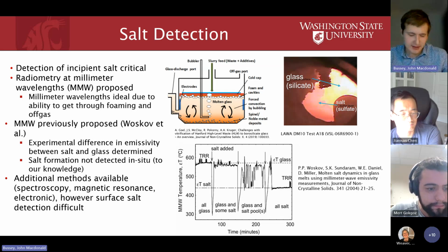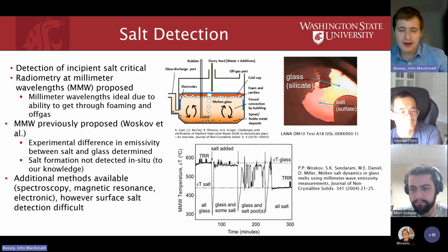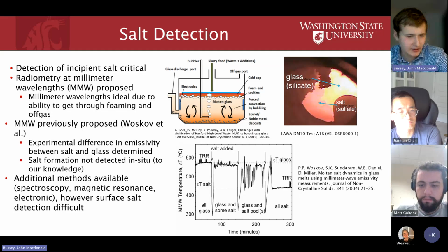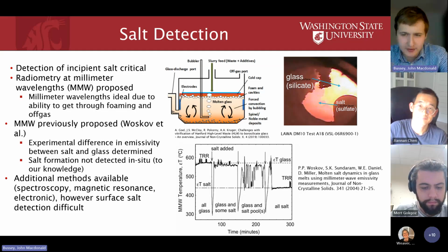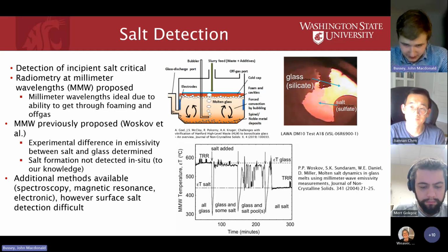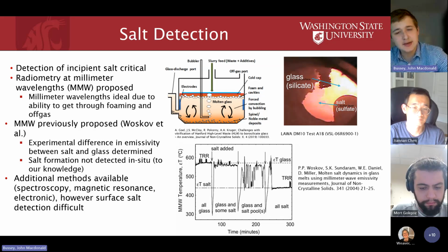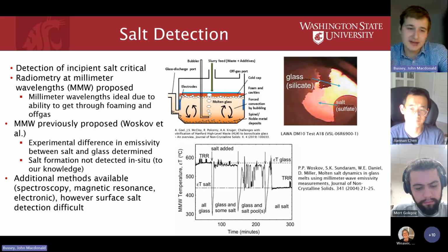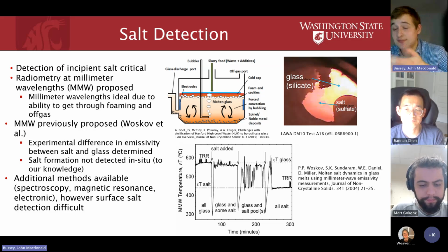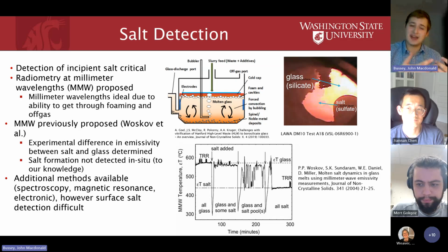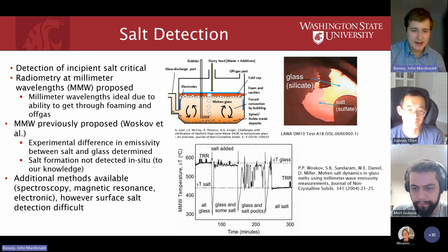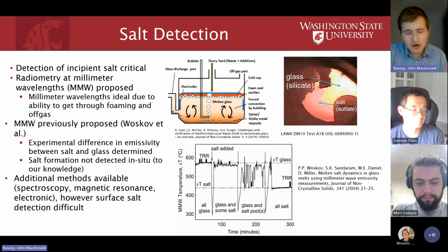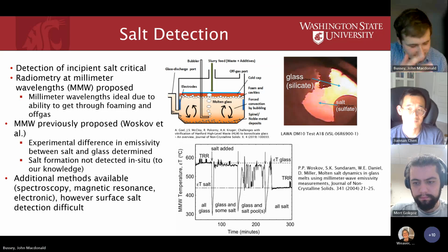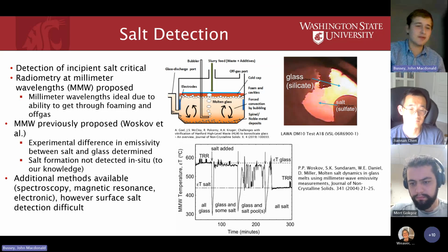understand a variety of systems for space exploration, for coal gasifiers, and this was another area where it was meant to be used, and they did some initial testing, and they showed that you could see a difference in the emissivity of salt and of glass. And so since this method tells it pretty much from this radiometric signal, you can decipher differences in emissivity. Since they showed that you can see salt, it seems like it might be worth a try. But that was 20 years ago.